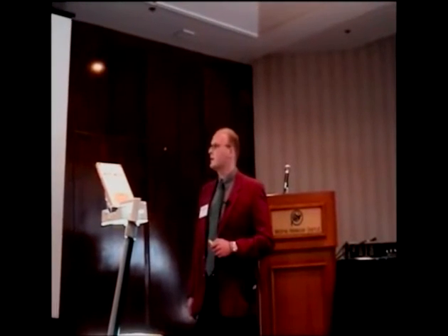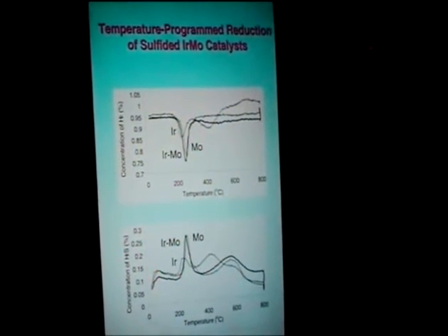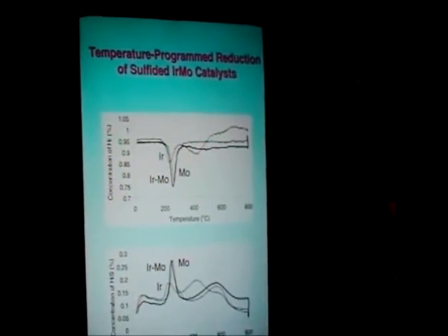Iridium reduces the sulfur bond strength and creates more vacancies, more sulfur vacancies. So this is, in our mind, the reason for the enhanced activity in comparison to molybdenum sulfide.